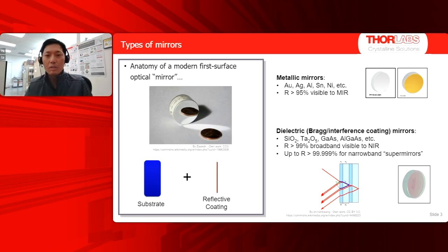And if you needed more, you'll have to go to these dielectric or interference coatings. They're made up of alternating layers of high and low index materials, often silica and tantalum oxide. You'll see our mirrors are actually made up of gallium arsenide and aluminum gallium arsenide, but the principle is the same. So these can easily give you above 99% reflectivity in the visible and in the near infrared. And if you want the ultimate reflectivity, the state of the art would be to get something like 99.999% reflectivity. Often this will be at the cost of being much more narrow band, but you get this level of high reflectivity. And I will term mirrors with such high reflectivities supermirrors.